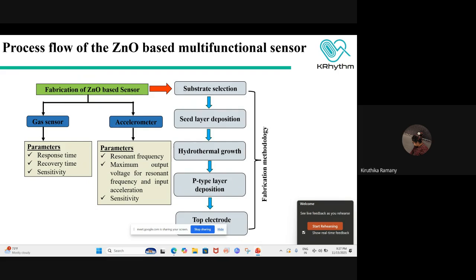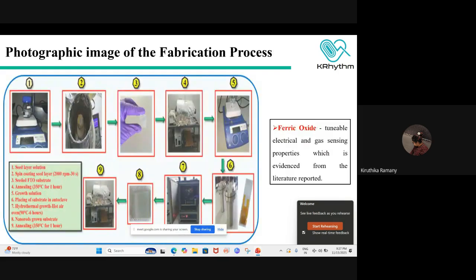For the gas sensor, the parameters that we are going to evaluate are response time, recovery time, and sensitivity. And for the accelerometer, they are going to be resonant frequency, maximum output voltage for resonant frequency and input acceleration, and the sensitivity. So this is a photographic image of the common fabrication process that we go for in all sensors in our laboratory. So the preparation of seed layer solution, spin coating of the seed layer at a specific RPM and duration, and then the seeded substrate would be annealed, and the growth solution would be prepared.